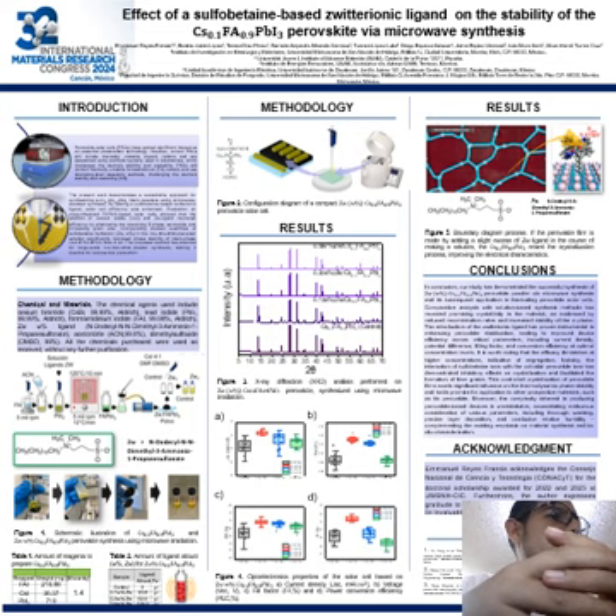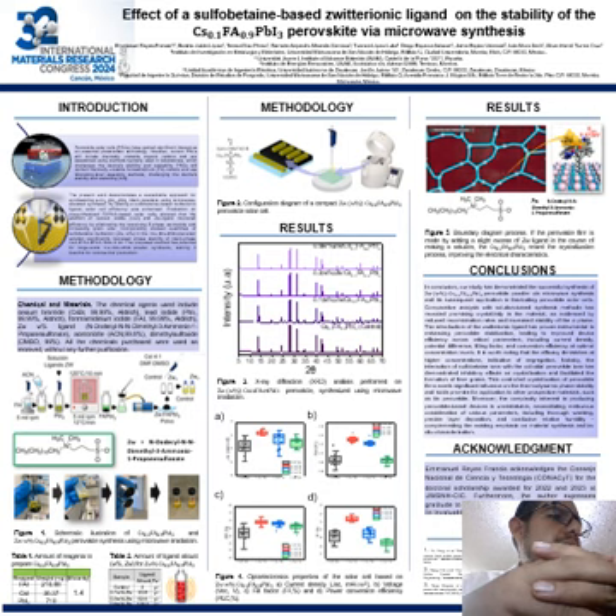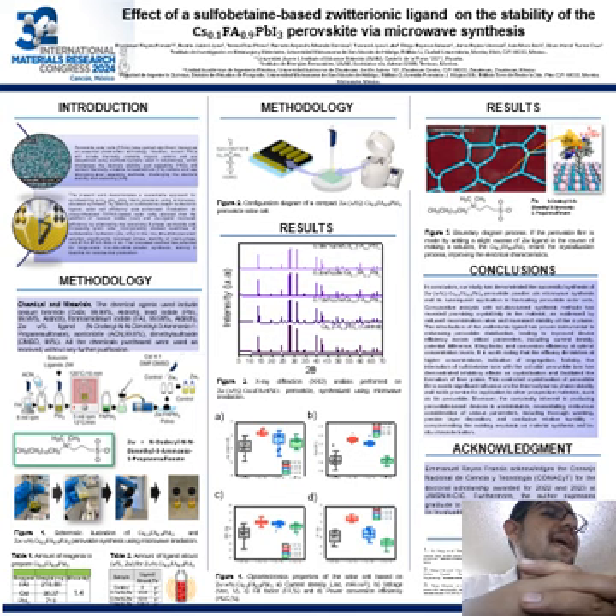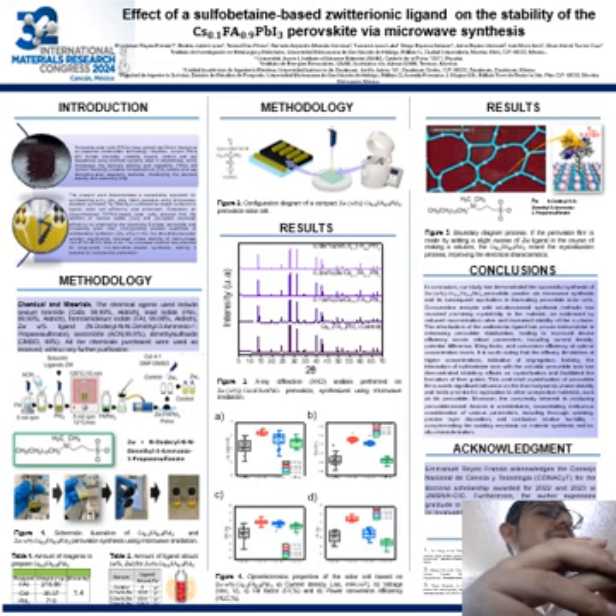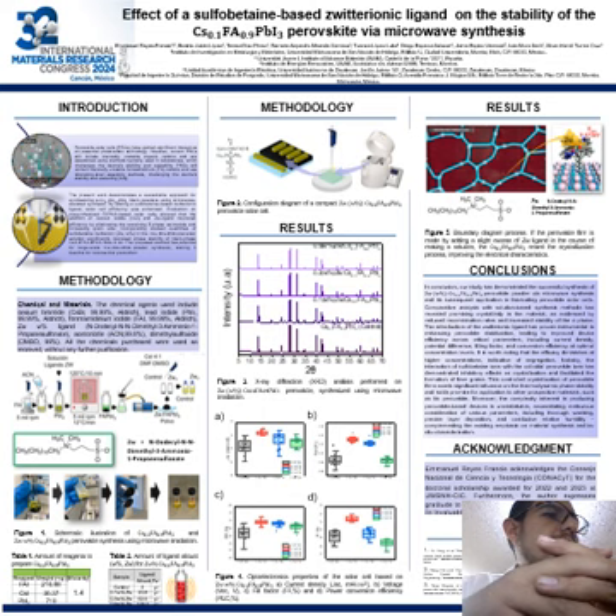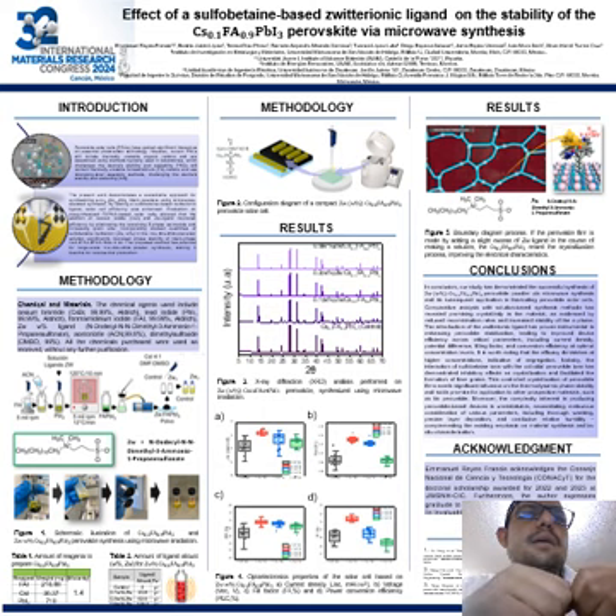lead iodide. For the development of the samples, we have to use different aliquots of the zwitterionic ligand stock solution. For this kind of synthesis route, we use 121 centigrades for 10 minutes, with a heating ramp of almost 12 centigrades per minute and stirring at 5000 rpm. Upon removing the vial, we obtain a black precipitate powder that we can observe in the image, and then we use vacuum to remove the greenish residues.